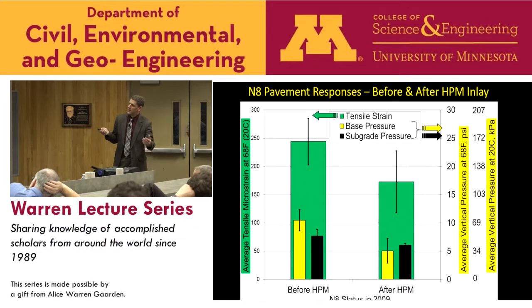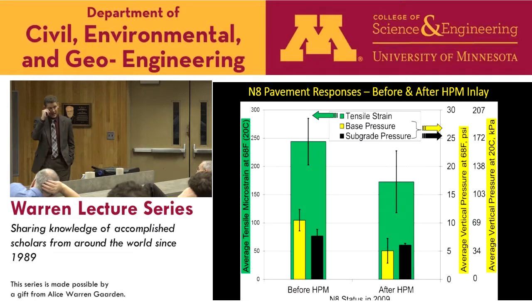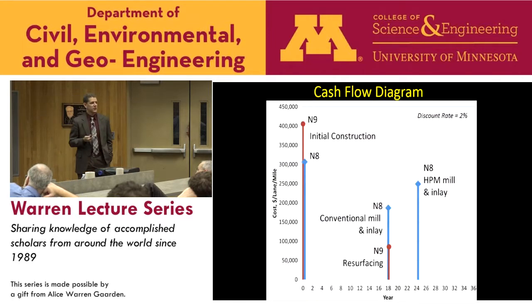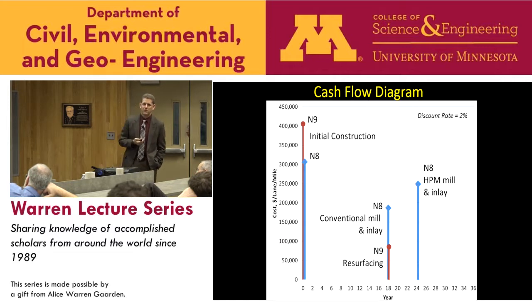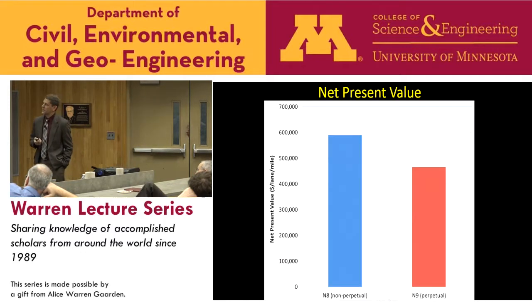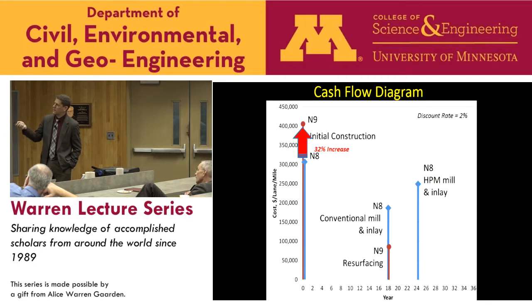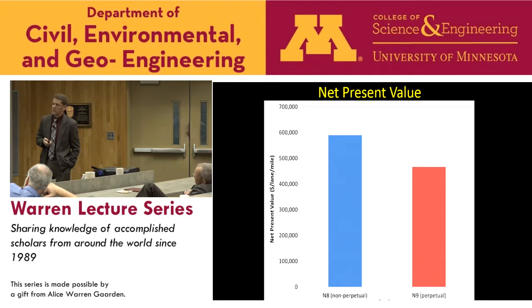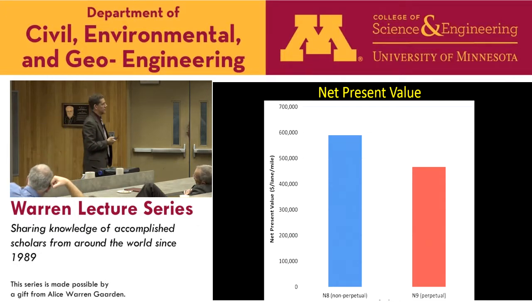And this is just looking at measured pavement response in section N8, the non-perpetual, before the high polymer repair, after the high polymer repair. And you see a reduction in the strain. That goes along with the increase in the modulus, and then also a reduction in the pressures, which are those dark colored bars. So that high polymer mix did have an impact on the structural integrity of that section. How expensive was it? Initial construction was 32% more for that extra 4 inches. But if you put together a cash flow diagram, of course we have these other repairs out here, but if you bring it back to net present value, it's actually 26% cheaper to build that perpetual section. So it is economically viable.